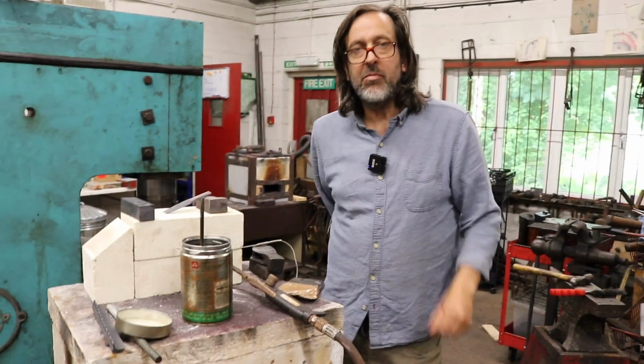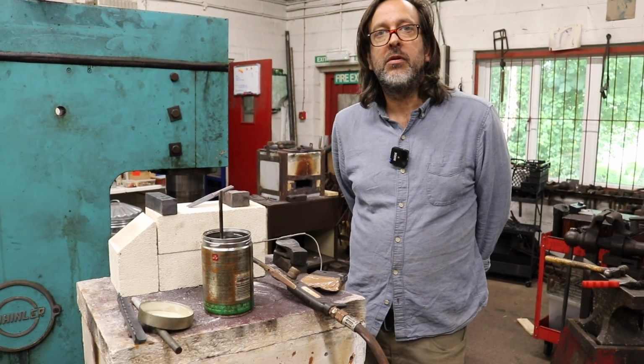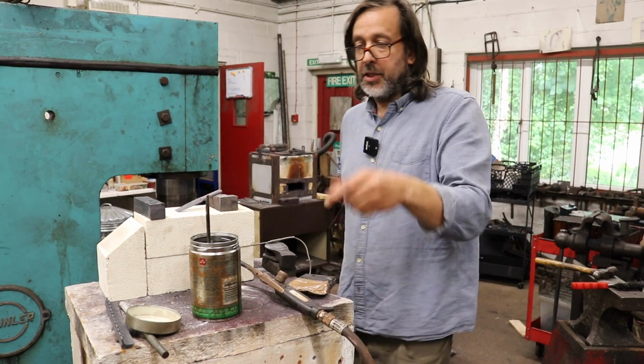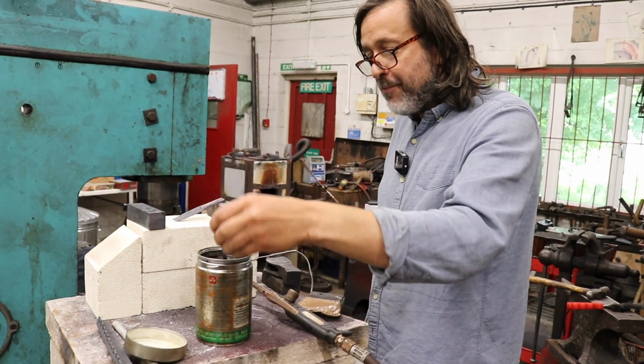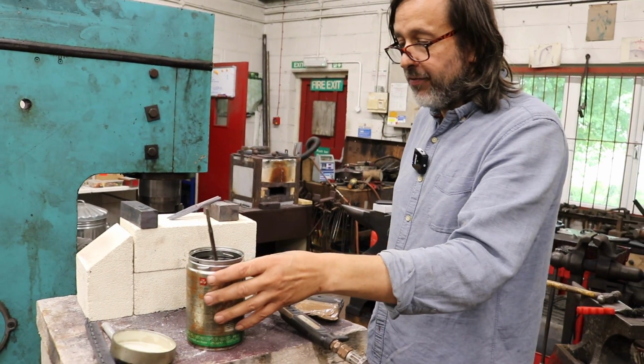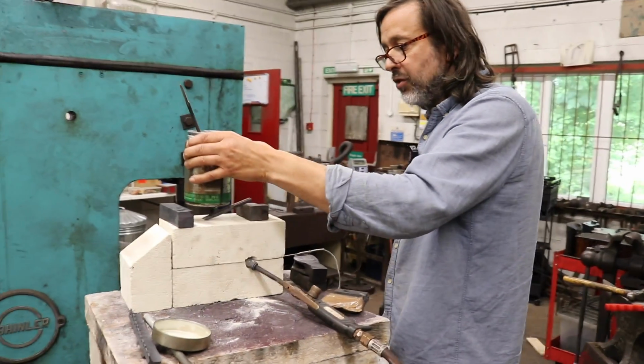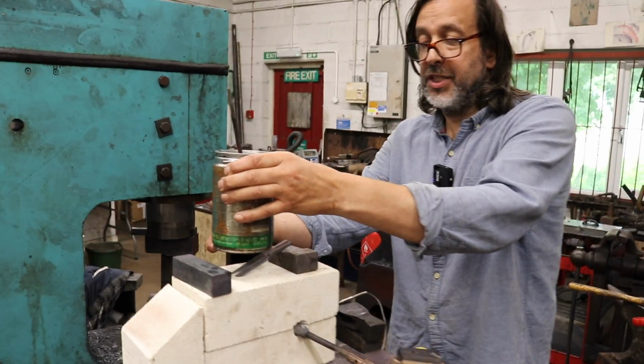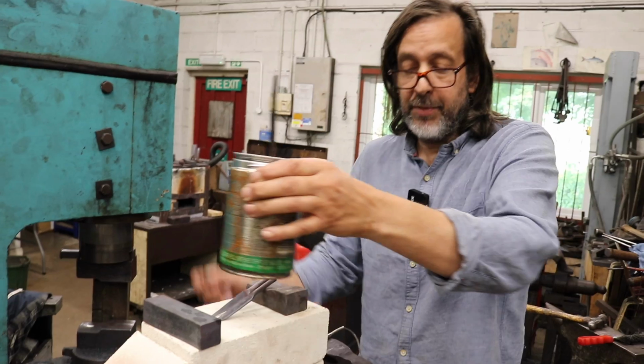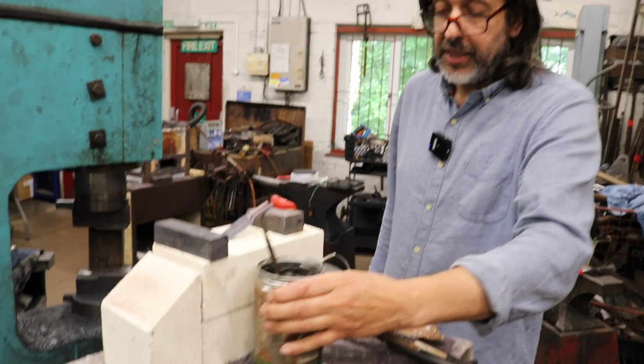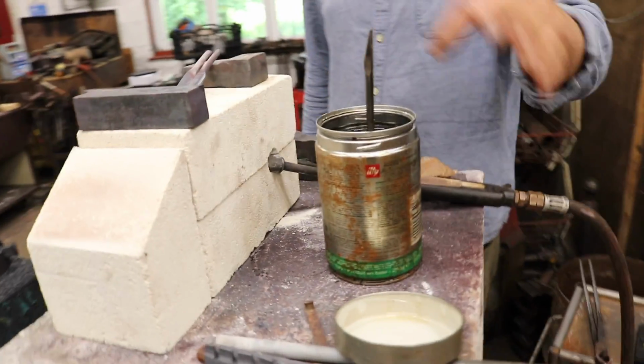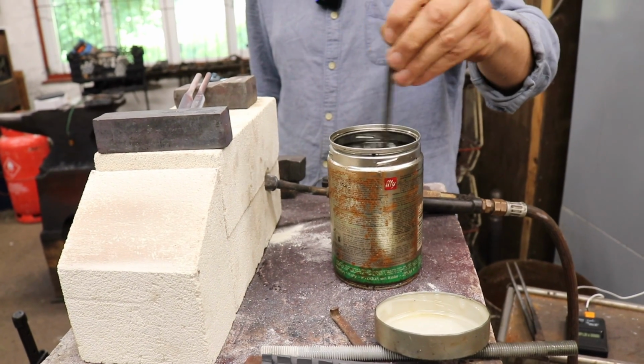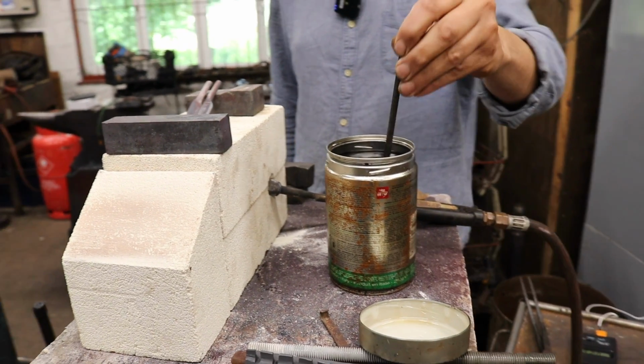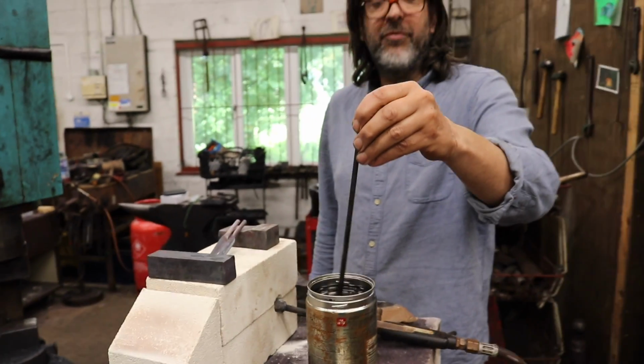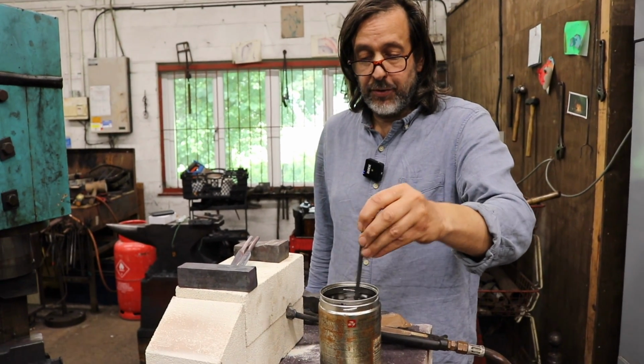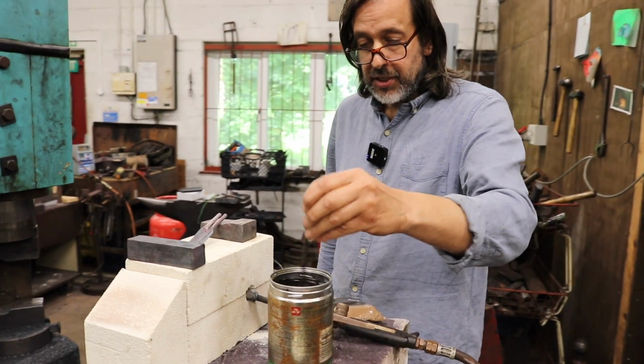So one thing we were doing just off camera as we were preparing for this scene is, you mentioned the importance of mixing the oil when checking the temperature. That's true, and I did just mix it without saying why. If you're heating it on top of something, that tends to work quite well because it's heated from the bottom and it'll mix quite well. But when I put it against the side, it'll be very hot at the surface and cool at the bottom. So just mixing it up and checking the temperature is much better than just putting a thermocouple in at the top and thinking the temperature of the top is the same as the temperature of the bottom. So giving it a stir is important.